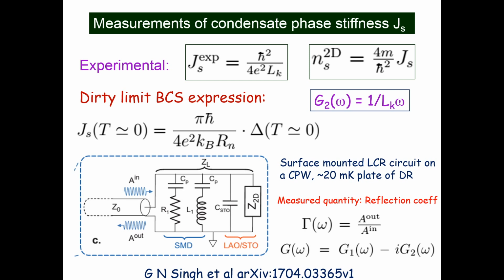And this is a little difficult experiment. It was done using microwave reflection experiments. So we had a coplanar waveguide on which you mount your strontium titanate lanthanum aluminate sample, and then you also have surface mounted components, capacitors and resistors and inductors.